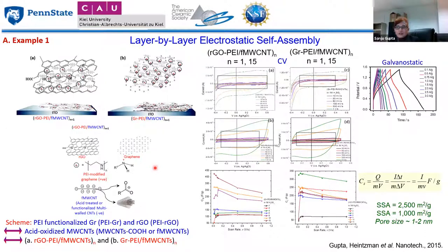So this was a classic graphene, actually a monolayer graphene dispersion, and we also use the reduced graphene oxide, because graphene oxide is not as conductive as reduced graphene oxide. Reduced means we are removing the oxygenated groups, and reduced graphene is considered an equivalent of the classic graphene, because classic graphene is not easy to play around with. It's limited, because you have to peel it off once you grow it, so it's heavy processing. But we compare these two together.